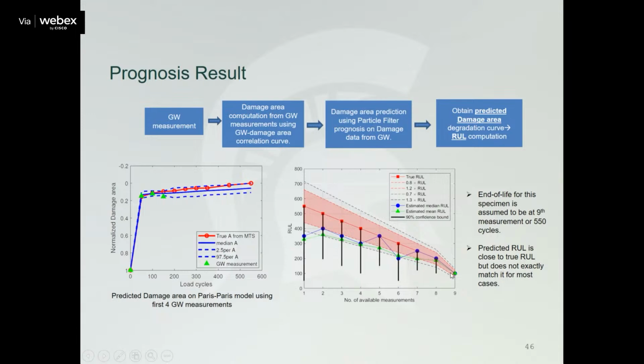So the end of life for the specimen is assumed to be at 550 cycles, and the predicted remaining useful life is close to the actual remaining useful life. Although it does not exactly match for most of the cases here, it demonstrates the capability of obtaining the RUL from the developed model and guided wave measurements.